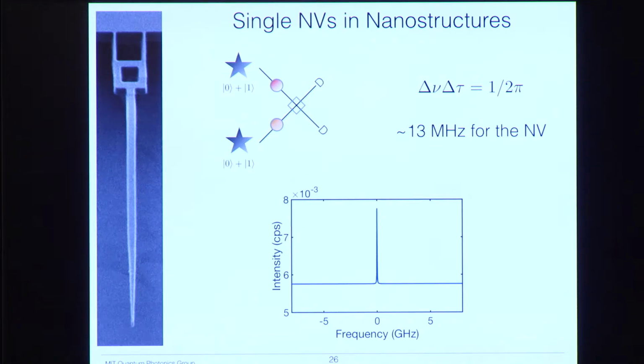So now we're back to the issue of spectral diffusion. And the worry is that all the surfaces that are now nearer to the NV center, because we've done all this fabrication, will have more defects, which will cause more electric field fluctuations, which will then cause more spectral diffusion. And so what we'd like to see is that the line width of a single NV center is what we expect by looking at the lifetime. So we call this the lifetime limited line width, which just means that there's this relation, and we know that the lifetime is about 13 nanoseconds, so you'd hope that the NV linewidth would be about 13 megahertz. And so that's what it should look like.